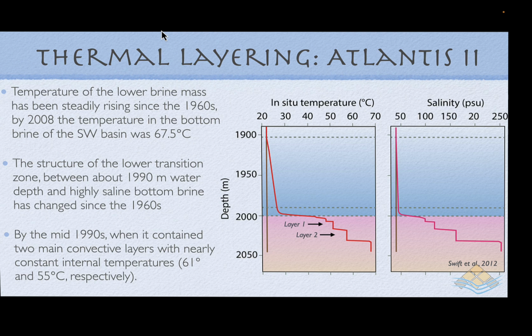That thermal stratification is also reflected in the same levels in terms of the salinity profile. Now, the temperatures are relatively stable, but they do alternate, they do rise and they fall according to how much hydrothermal input we have coming into that lower brine pool. So the temperature of that lower brine mass has been steadily rising since the 1960s. And so by 2008, the bottom temperature had risen from around 61 degrees to 67 degrees.